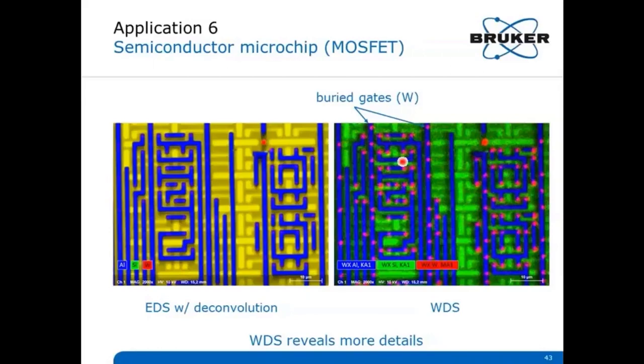And you can see tungsten in the EDS image only in this spot here where the top layer is degraded by mechanical influences. So EDS can see tungsten only in these damaged places, and is not sensitive enough to see where the tungsten is elsewhere. So WDS reveals much more details. It is much more sensitive, and therefore it can show the distribution of the buried gates of the MOSFET, which are not seen by EDS.